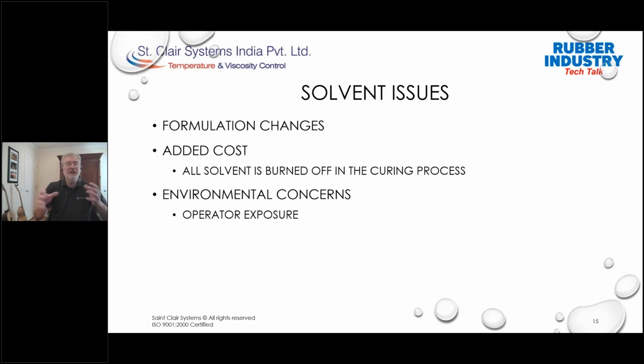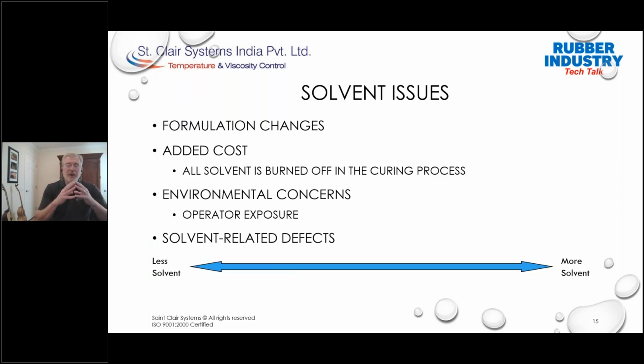Now, to make matters worse, too little or too much solvent can cause defects. And we can plot these defects on a continuum as we see here. Now, if we have too little solvent, we get dry spray and all of the associated issues with adhesion and all of the other issues that you're used to, uneven coatings, etc. If we add a little more solvent, we reach the optimal point at which we should be using the product to get the optimal performance level.